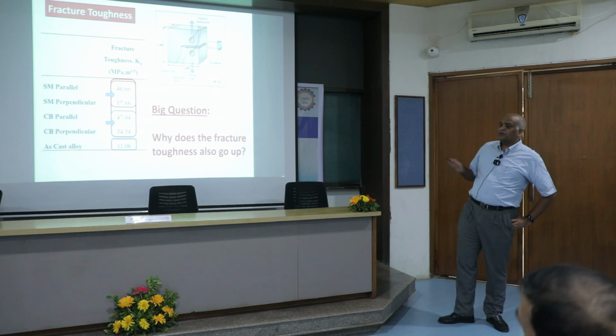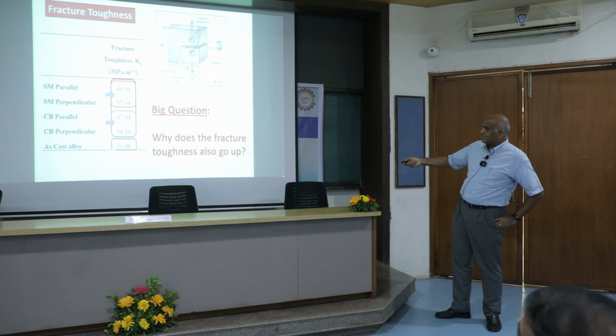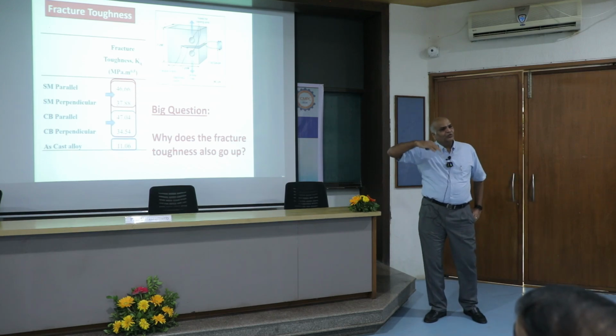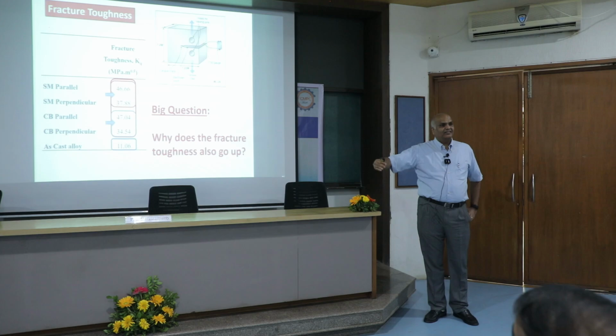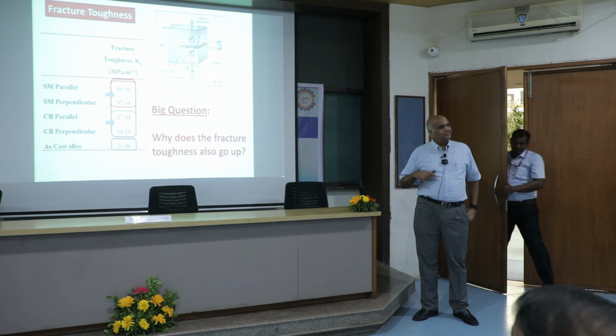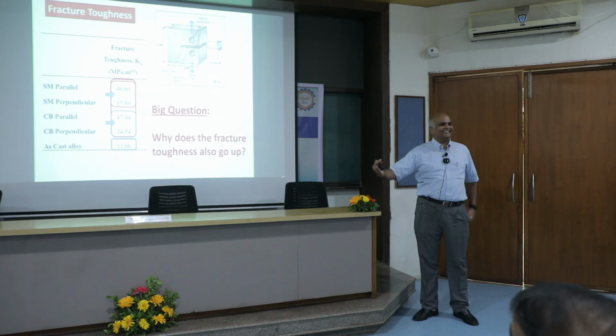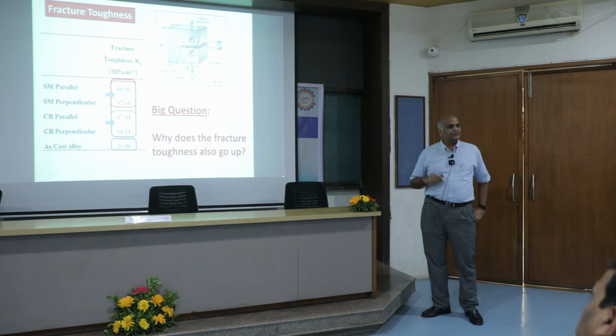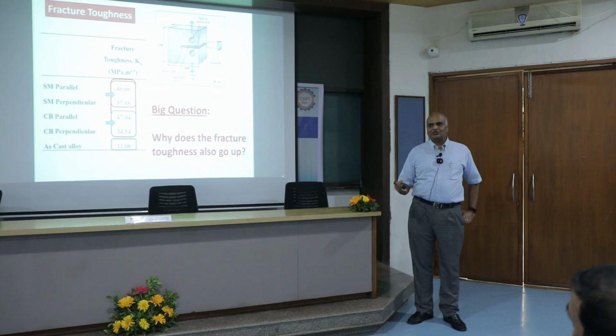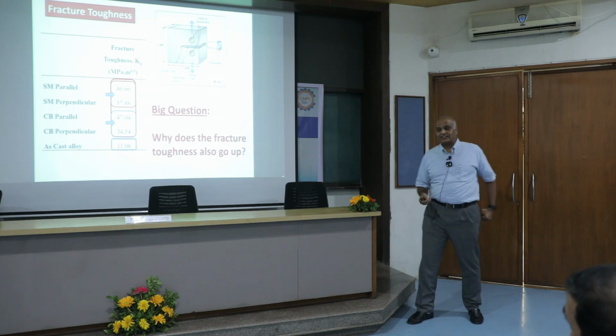Okay, this is where experimental things are fun. So when we tested proper fracture toughness measurements, so I told you, right, cast alloy's fracture toughness is 11 MPa root meters. We were expecting it to go to 1 or 2 MPa root meters, but to our surprise, the fracture toughness has gone up. It's not 11 MPa root meters, it has actually gone up, not by 100%, but by 400%. Look at these numbers, right? It's much more anisotropic, but fracture toughness has dramatically gone up, which was a very surprising result to us, okay? So why does this go up, okay?